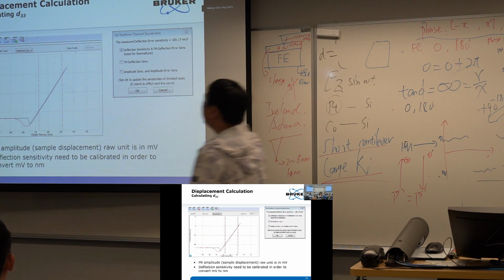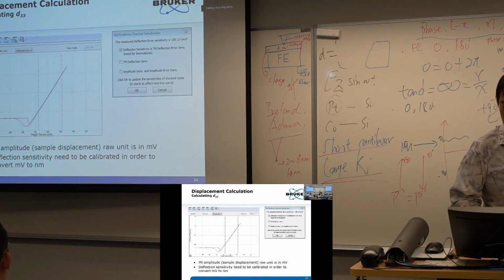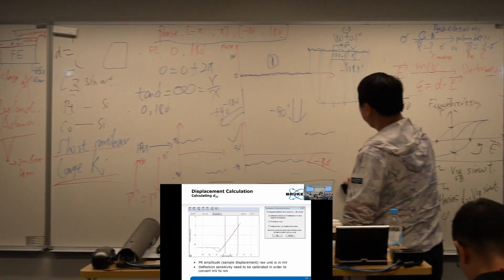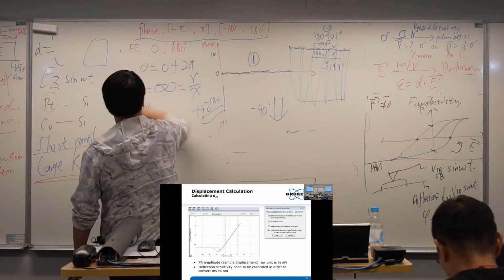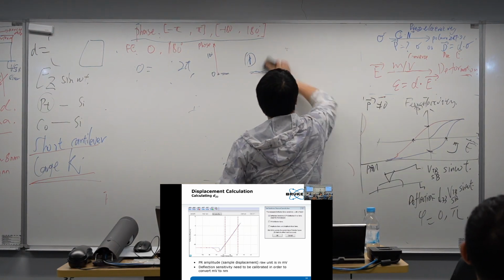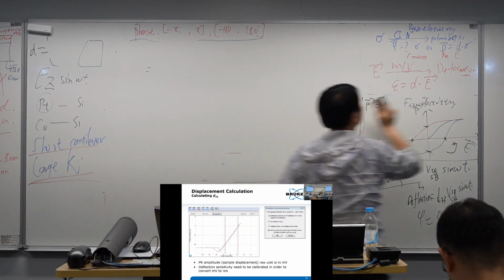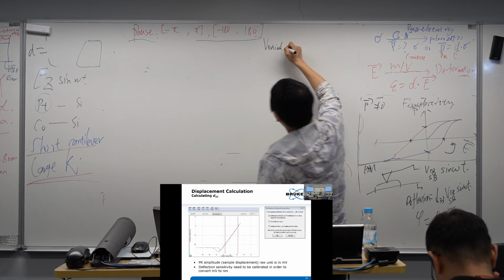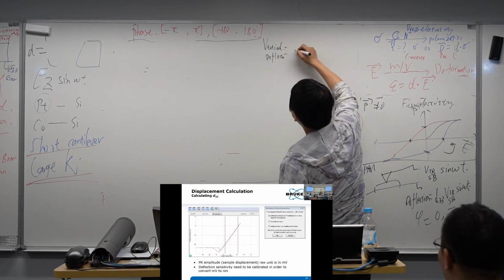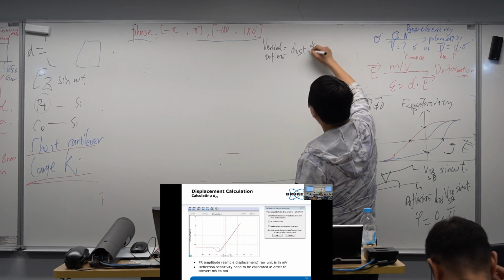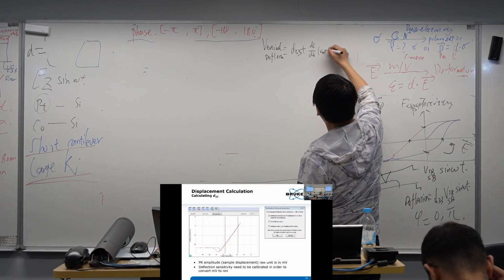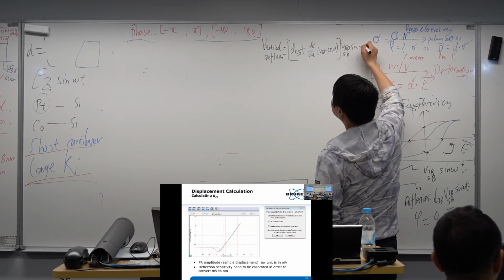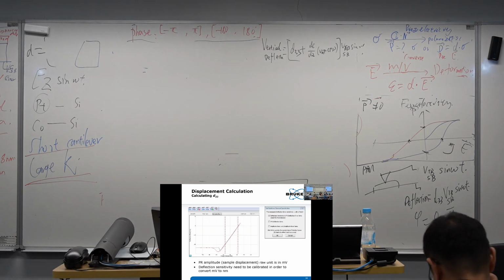Next, if I want to calculate my d33, my theory is the vertical deflection equals d33 plus dC over dz times V_DC plus CPD, times V_AC sine omega t. Right? That's the basic of our PFM.